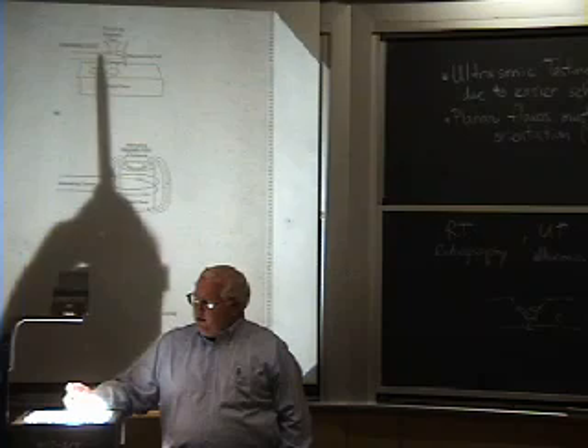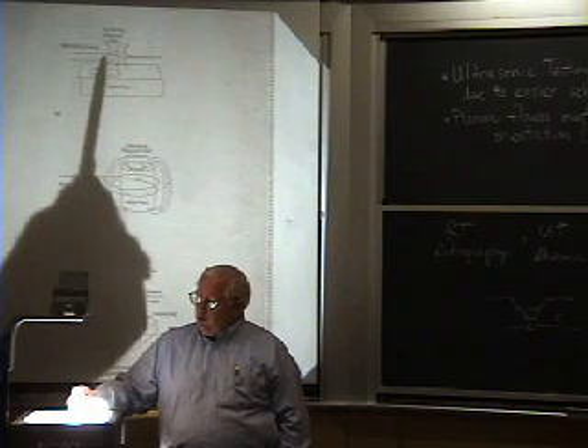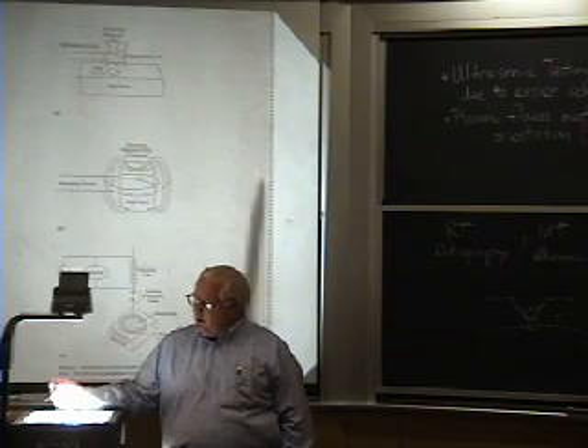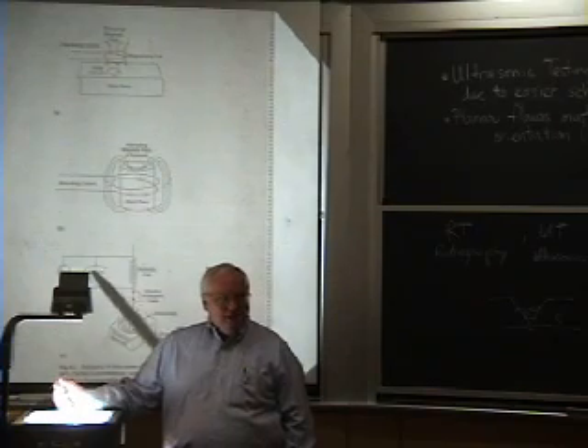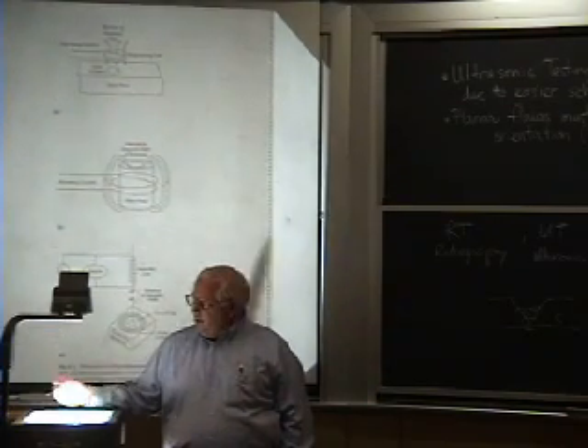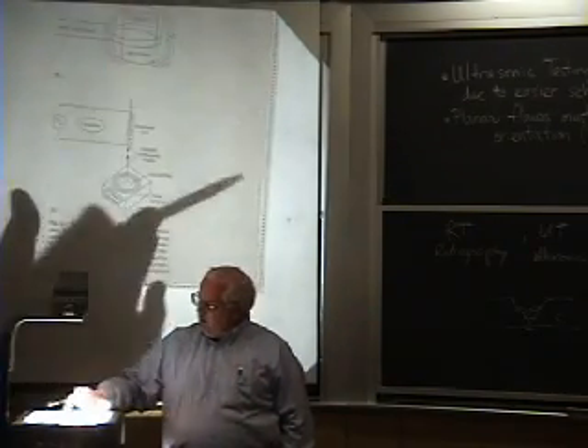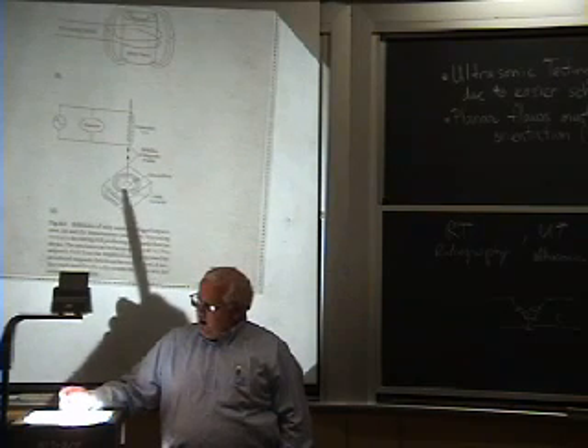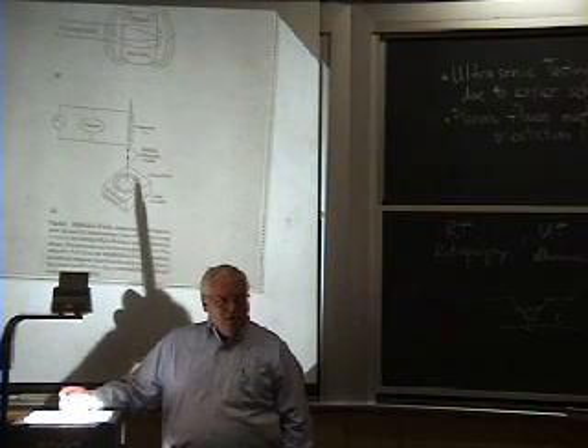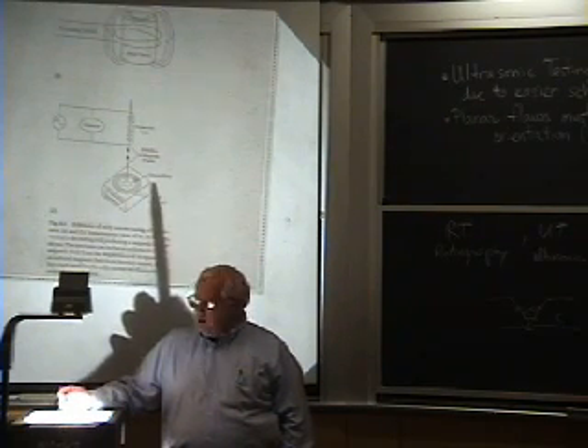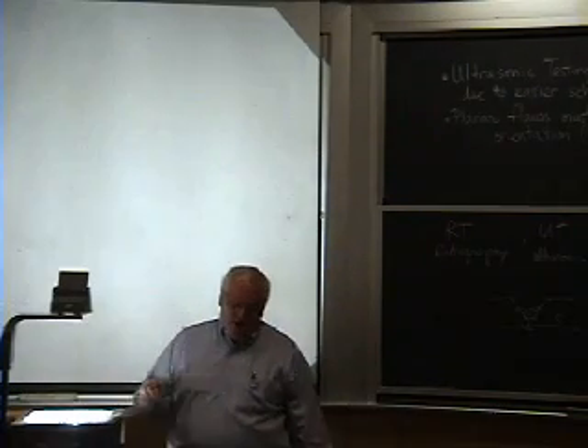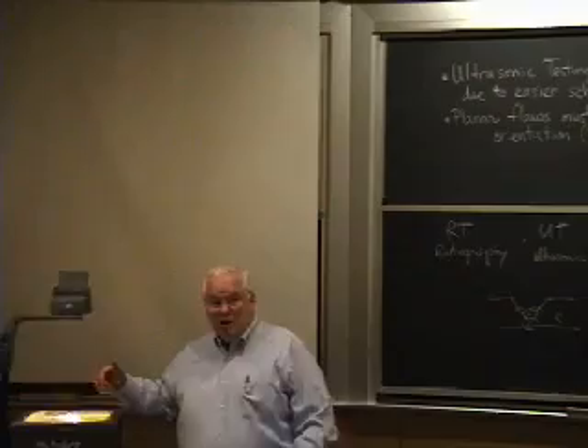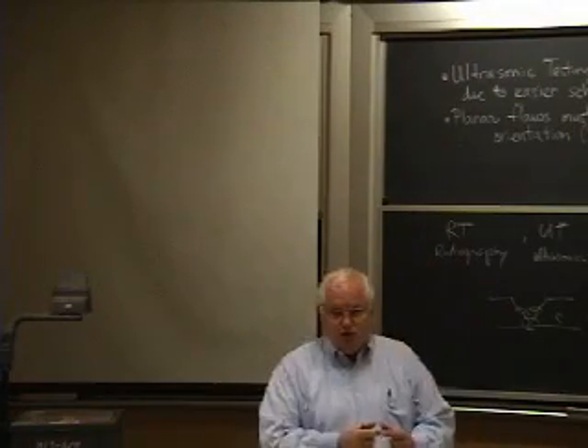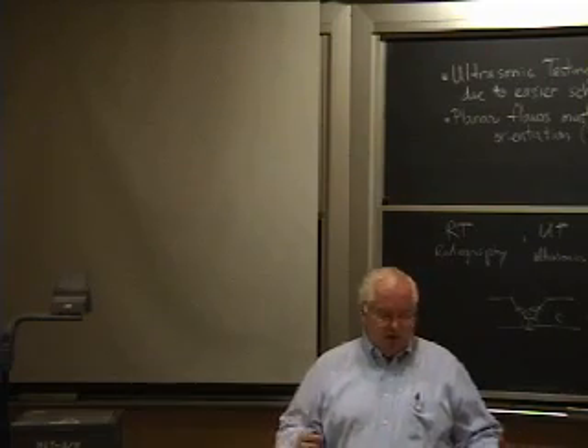So what you're going to do is use this probe field, and then you'll have a second coil which is going to try to detect the magnetic field. And if you have any discontinuity, what they're showing down here is a little discontinuity, and the magnetic field, or the current going through there, is non-uniform, that's going to give you a magnetic discontinuity similar to the magnetic particle testing, and you can pick that up. Now, the advantage of eddy current over a magnetic particle is eddy current can be operated at 100 kilohertz. That means that you can test things very, very rapidly.